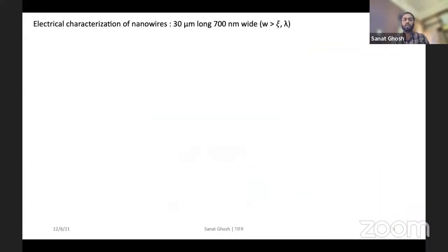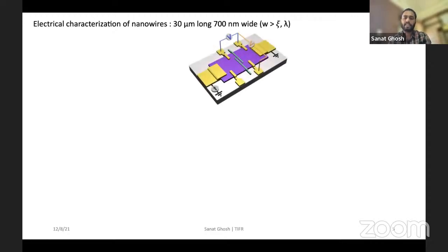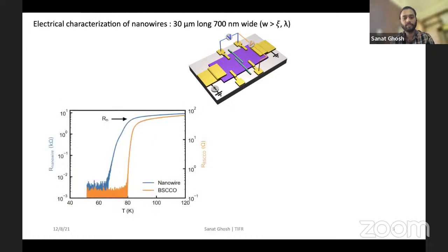So I will mainly focus on nanowires that we make by this method, which has a length of 30 micron and 700 nanometer width. For the measurement, we first do electrical characterization, and the measurement schematic is shown cartoonly here. We simultaneously measure the response across the nanowire and also the pristine BSCCO, to make sure that during the fabrication steps the BSCCO is intact or of good quality.